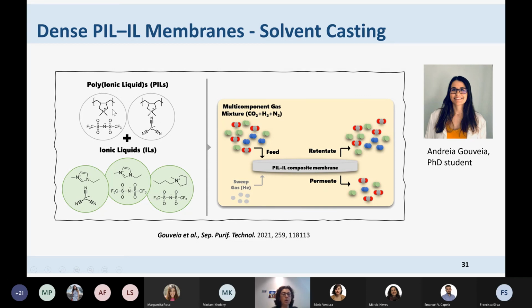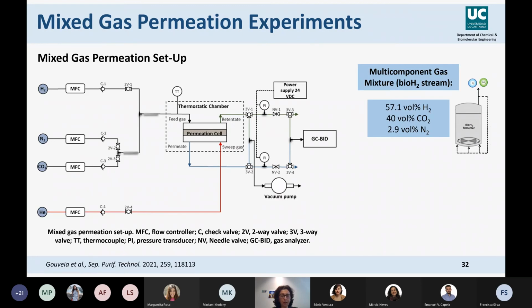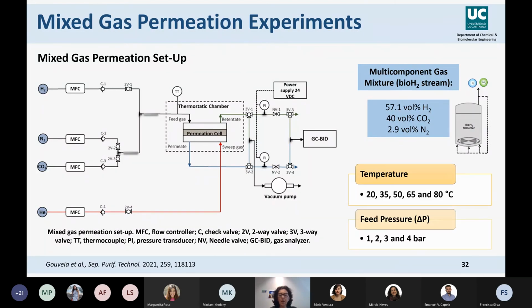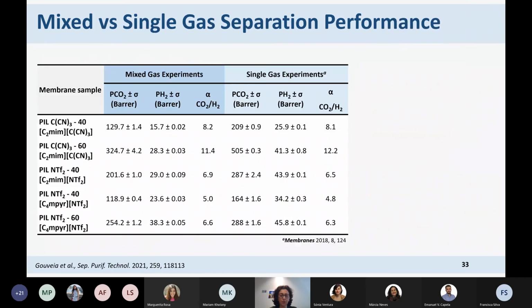So as I told you, I'm not an organic chemist, and so what we do here is we buy this polyelectrolyte with chloride, and then I just do an ion exchange, and here an ion exchange also. We've already tested and know that NTf2 combined with C(CN)3 are the best ions to perform CO2 gas separation. And so those are the ones that we are going to use here. Okay, so this is the apparatus that we used. We used this in collaboration with the University of Cantabria, Santander. And we did this at several temperatures and feed pressures.